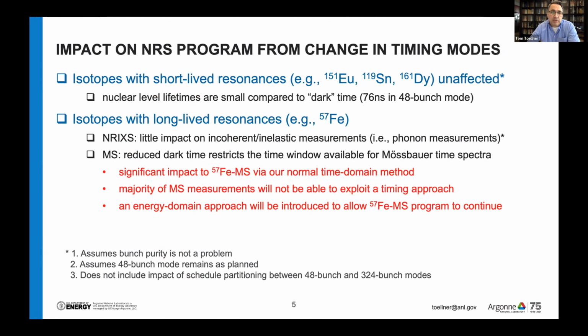For both NRIX, the phonon measurements that is, as well as Mössbauer spectroscopy. I put an asterisk there because there are some caveats to that. There are some listed at the bottom here. I have 3 caveats. One is associated with bunch purity, which is simply not known. In fact, all 3 of these are known unknowns, if you will.